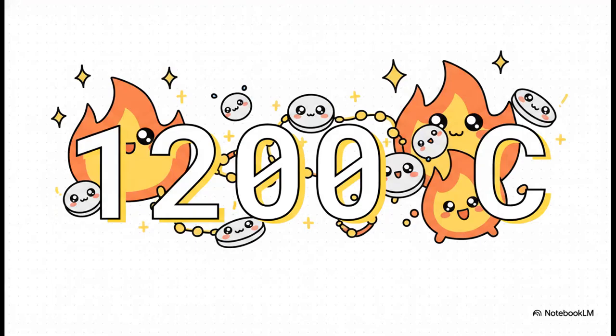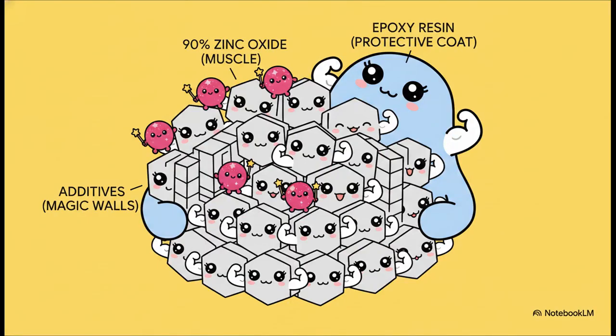And when I say firing, I really mean it. During this sintering phase, those little ceramic discs are baked at scorching hot temperatures, sometimes reaching up to 1,200 degrees Celsius. This intense heat is what fuses the zinc oxide grains together, creating that all-important structure that allows it to work. Every single ingredient in that recipe has a critical job.